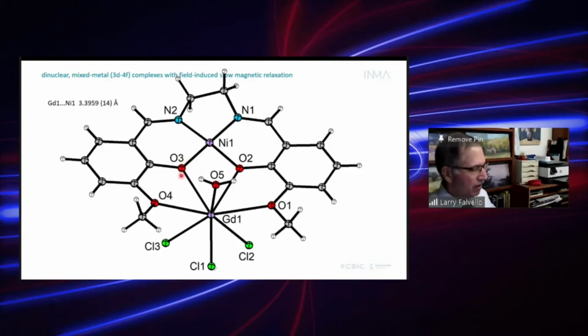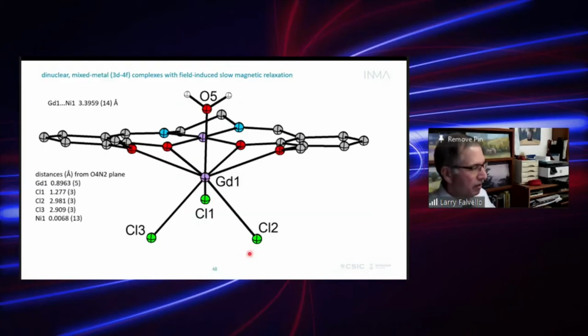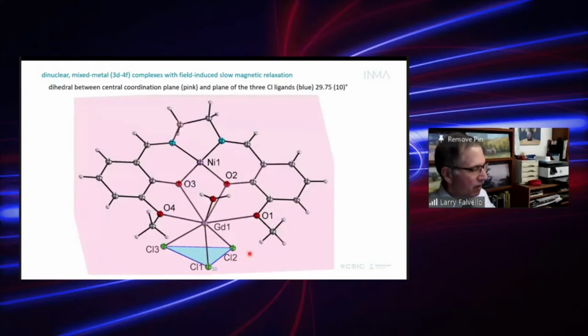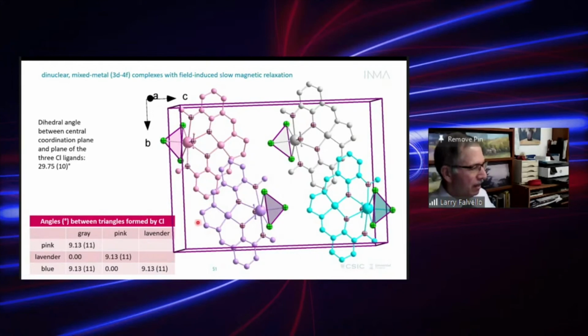We have a structure in which this large ligand and then a second group of ligands, 3 chlorine atoms in a triangle, are not parallel to each other. This is an anisotropic coordination environment around gadolinium, which leads, we think, to the slow relaxation. And it's an anisotropic structure that if we were to measure a single crystal, let's use the plane of the 3 chloride ligands as a reference for the 4 molecules in this case a monoclinic unit cell.